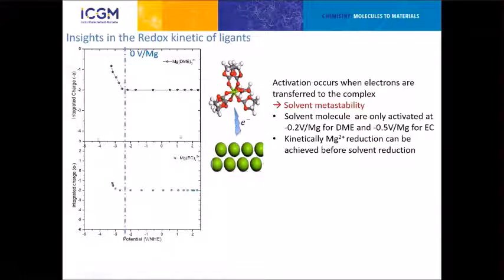In this case, what we looked at is the total charge of our complex with the magnesium and the attached solvent around it, first the solvation shell, and with that we look at the charge as a function of the potential. What we see is we really get a +2 charge most of the time, and at some point, an electron is transferred to the surface toward the solvated Mg2+, and some reduction occurs. This can give us a first hint of where the electrochemistry is going to happen.